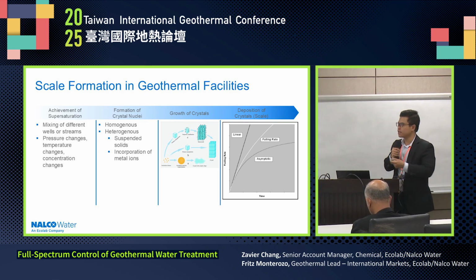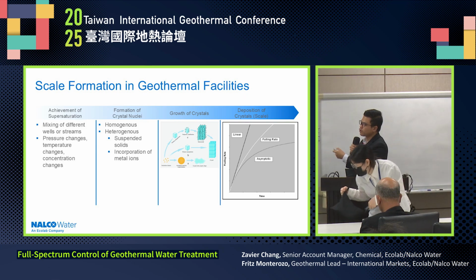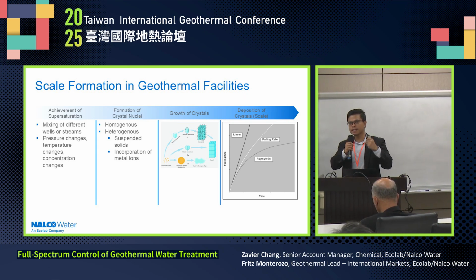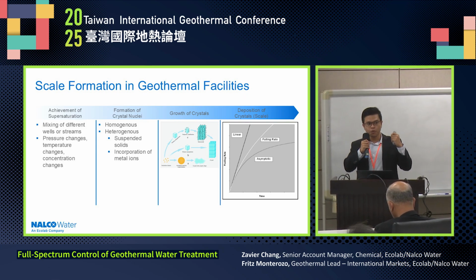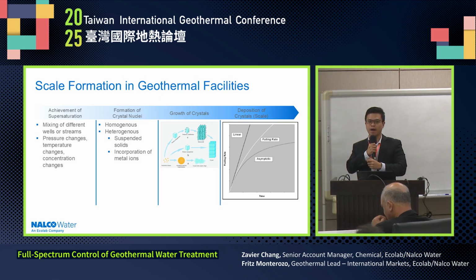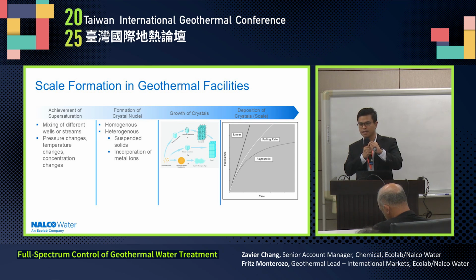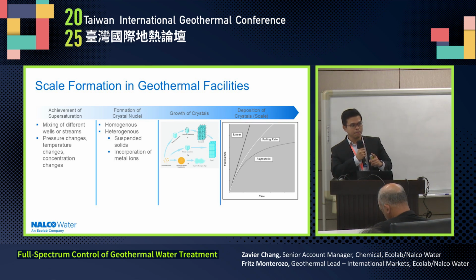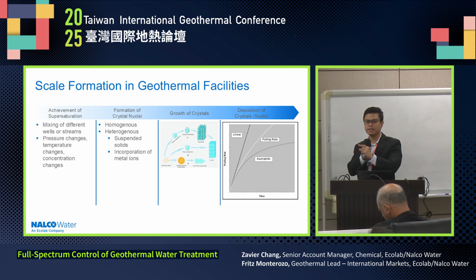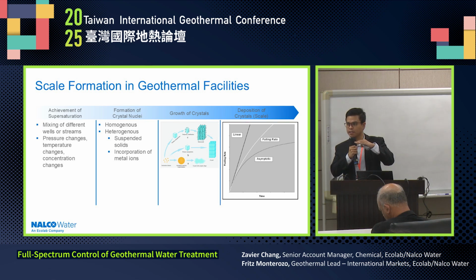summarized into 4 steps. First is achievement of supersaturation. So your system needs to be supersaturated first for scaling to happen. That's why we have this term called saturation index. So saturation index, we calculate what is the scaling tendency of a particular mineral. If your saturation index is less than 1, meaning it will not scale. If your saturation index is equal to 1, meaning it is saturated with respect to your solution, there is possibility